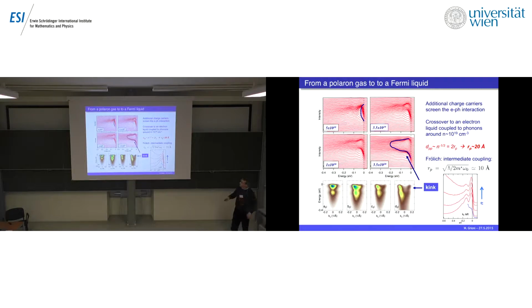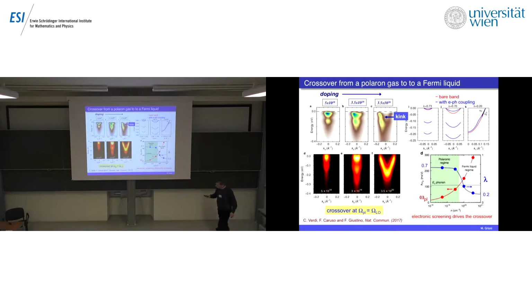Now, we tried to estimate the characteristics of this large polaron, but actually, at about the same time, or soon afterwards, we were very happy to see the calculations done in Giustino's group, and we will hear from the next speaker, which really explained what is happening. So these are the theoretical results compared to the experiment, and you will hear in a moment the whole story, but essentially what happens is that there is a crossover between a regime where you have isolated polarons and a Fermi liquid regime, and the crossover essentially happens when the energy of the plasmon crosses the energy of the phonon mode.